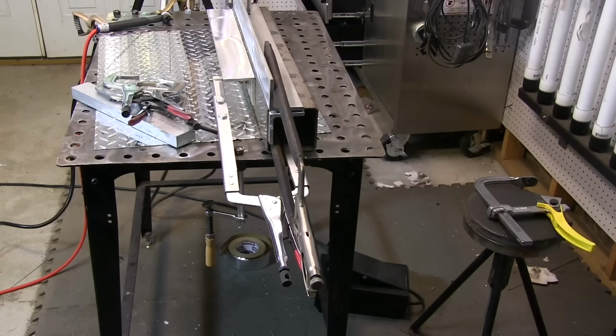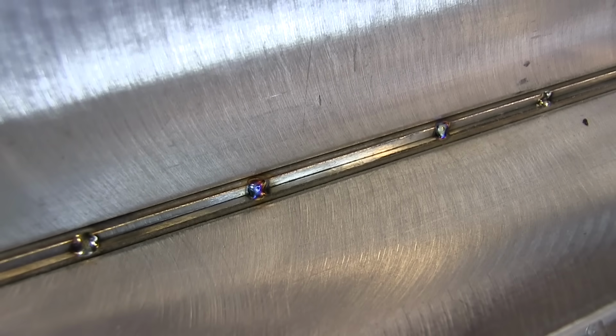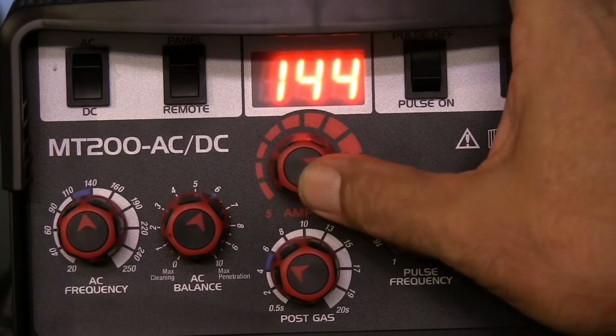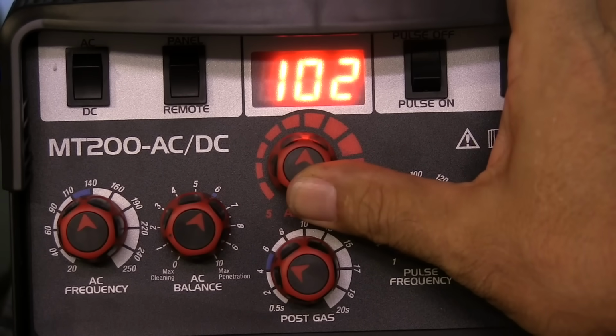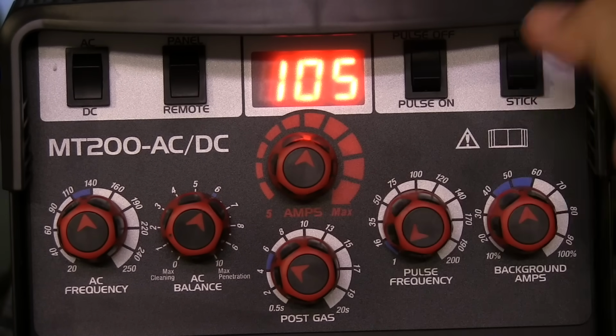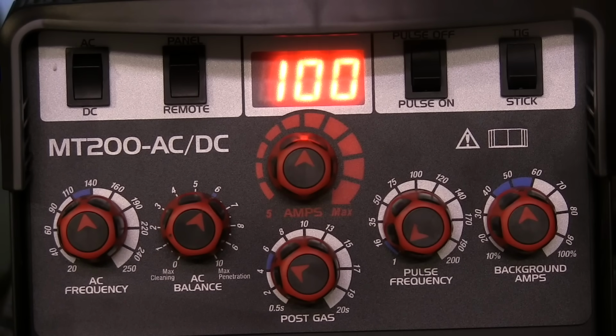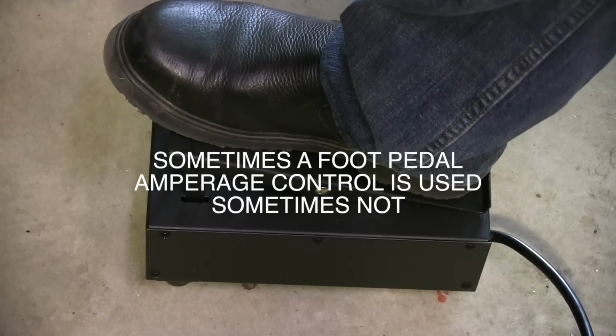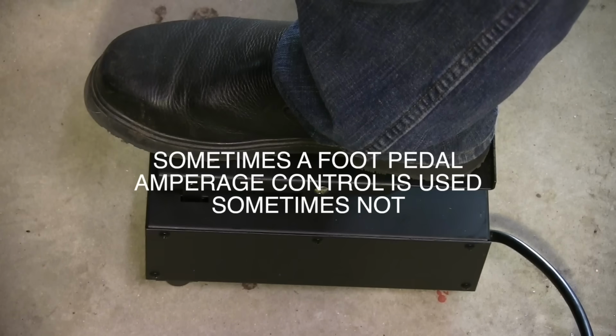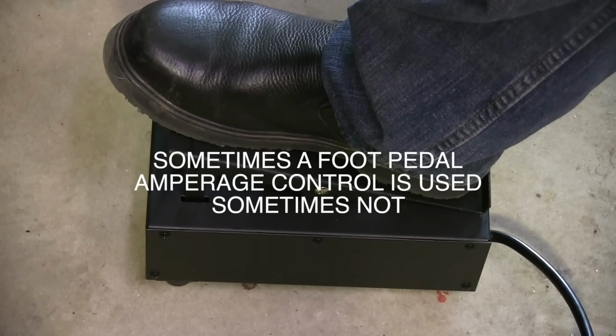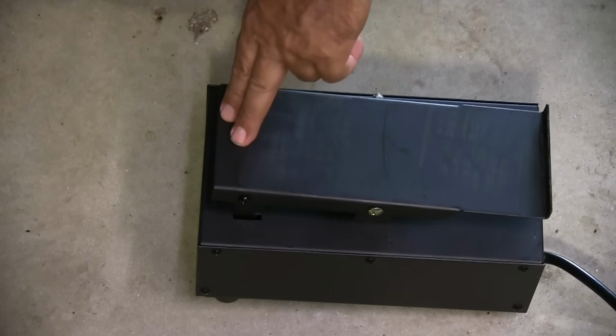Here I'm using some aluminum angled chill bars on a little stainless steel manifold, and it's about 1/8 of an inch thick, and on carbon steel I would probably use about 125 amps. Stainless requires only about 2/3 the amperage that carbon steel does. I'm using a foot pedal. Sometimes a foot pedal is used, sometimes it is not used in TIG welding. I prefer to use one whenever I can.